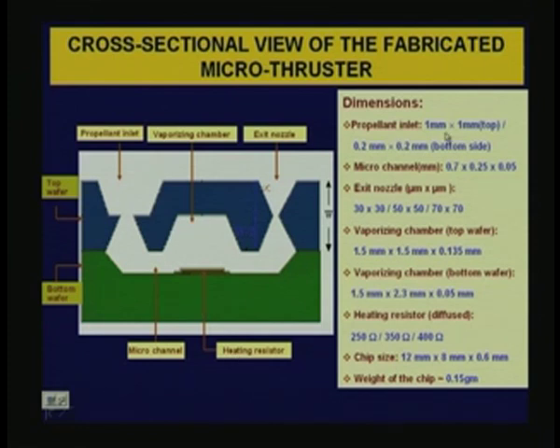The propellant inlet dimension in the top is 1 millimeter by 1 millimeter, bottom side 0.2 by 0.2 millimeter, because you see the propellant inlet here, the top dimension and bottom dimension are different. Micro channels are 0.7 by 0.25 by 0.05. Exit nozzles are of sizes 30 by 30, 50 by 50, 70 by 70. We have tested with different exit nozzles to see which is more efficient.